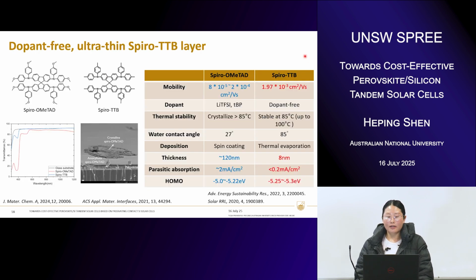Unfortunately, the widely used spiro-OMeTAD can allow good efficiency for the single junction, but has a lot of challenges in these aspects. For example, it has very low mobility, 10^-5 or 10^-4. That means we need dopants to make it highly conductive. We usually use lithium salt or tBP, some organic molecules. This causes a significant problem in terms of stability because they can migrate easily in the cell. Together with the low crystallization temperature of spiro-OMeTAD, stability is a big problem.